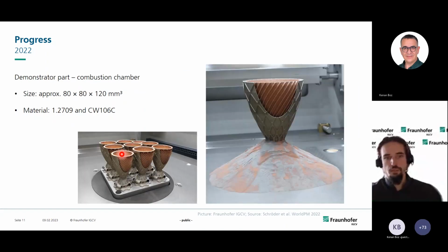And last but not least, you may know this part. This was one of our biggest demonstrator parts at the moment. This is the combustion chamber my colleague designed. It's 120 millimeters in height and still made out of tool steel and copper chrome zirconium. That's why, as you can see here, the powder is getting mixed within the process. So afterwards you've got a mixed powder and you need to separate it. Tool steel and copper chrome zirconium is very suitable for that, as the tool steel is ferromagnetic and the copper chrome zirconium isn't. So we have invented a mechanism which can separate the powders for us.